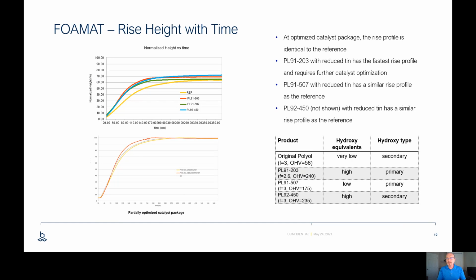Now, looking at the products that we're going to be talking about today, you can see in the table in the right-hand corner that the original polyol has a functionality of 3 and a hydroxyl value of 56, a very standard, very common polyol for this type of system. So the hydroxyl equivalents in that system are very low, and the hydroxyl type is secondary. The PL91203 has a high hydroxyl equivalent because the hydroxyl value is much higher, and we're considering primary hydroxyl type. Now the PL91507, because of its lower hydroxyl value, has a lower number of hydroxyl equivalents than the other resonance materials, but it also has a hydroxyl type that is primary alcohol.